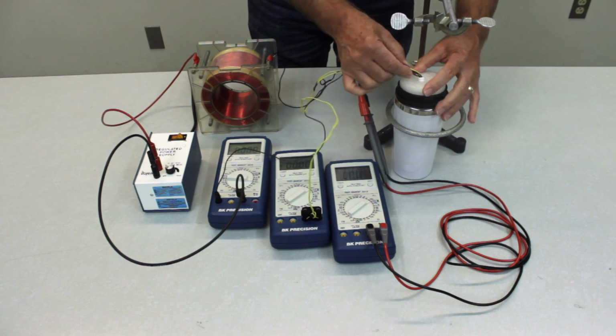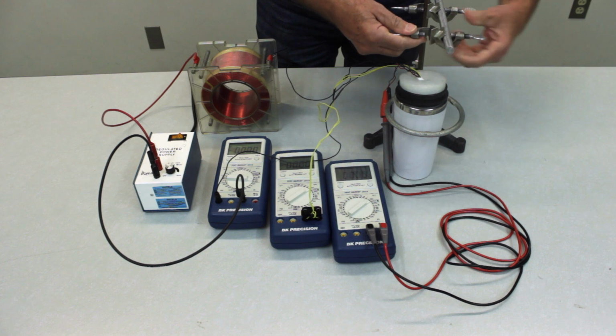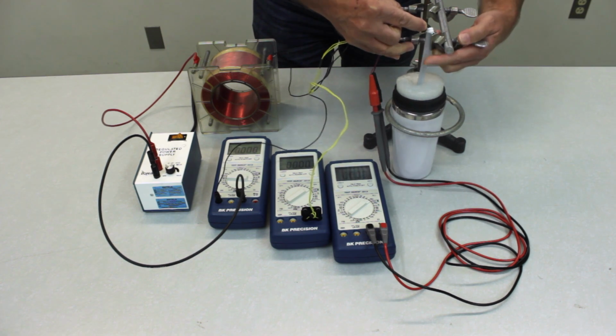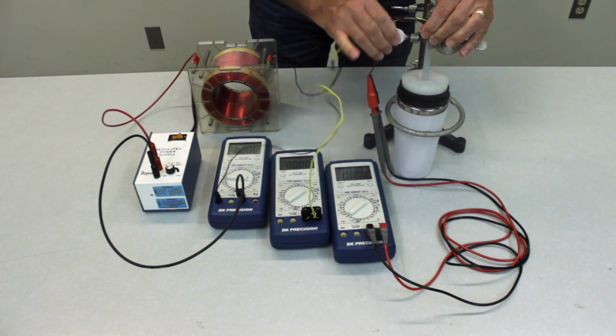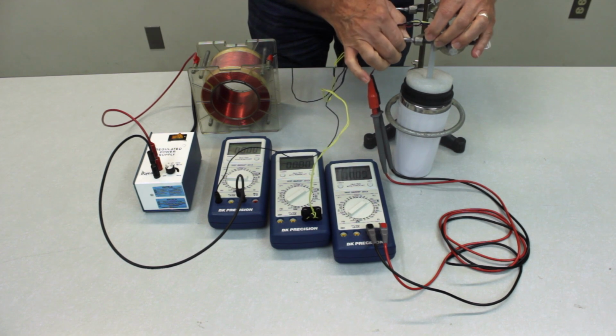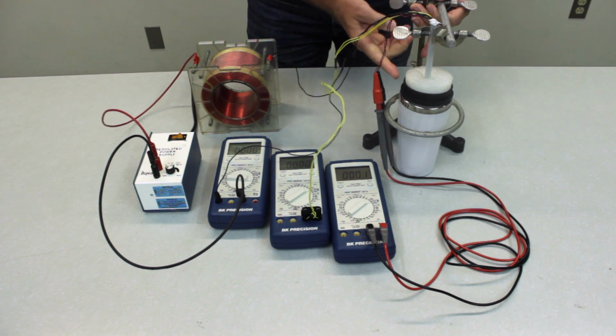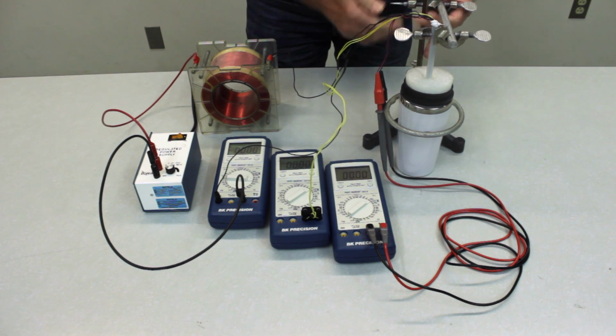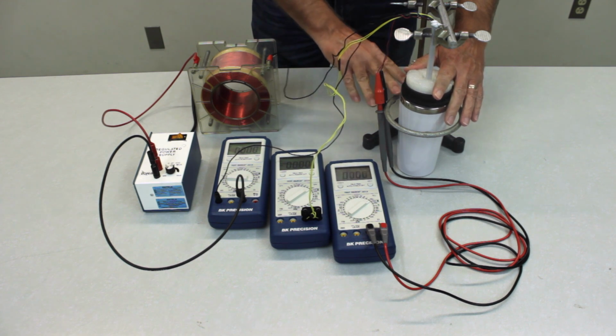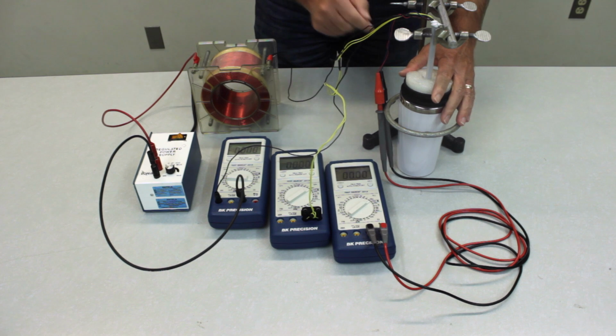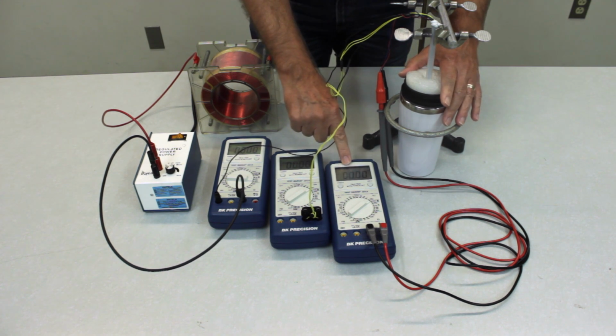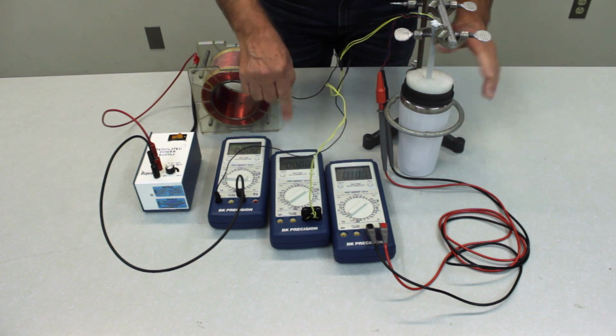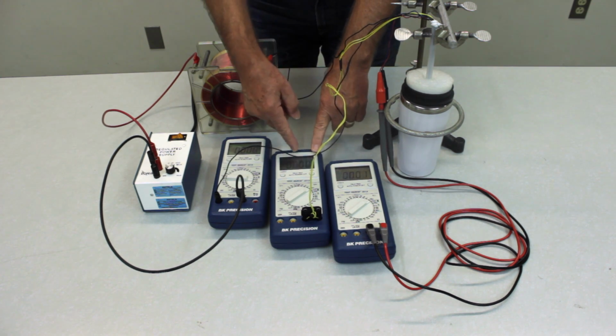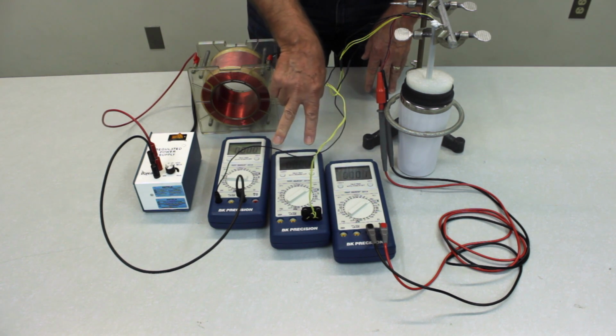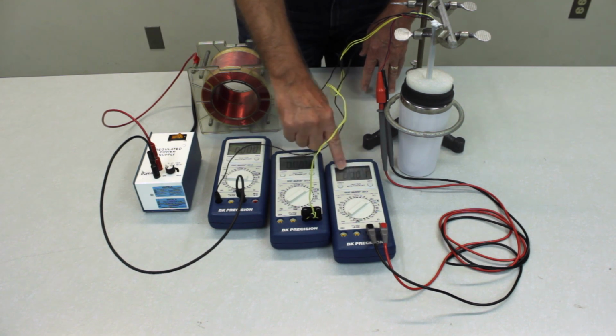But most of the data will be taken by lifting the sample out of the liquid nitrogen. So we'll just clamp the sample onto this stand, and raise it up out of the liquid nitrogen, but still underneath the insulating layer of the cup. That will keep it in a cold vapor environment, but above 77 Kelvin, so the sample will slowly increase in temperature. And what you should see is that the thermocouple voltage will slowly decrease from 6.4 millivolts on down, and the sample voltage, when you reach the critical temperature, will begin to reappear. So you want to take lots of good data, sample voltage as a function of thermocouple voltage, to find the critical temperature.